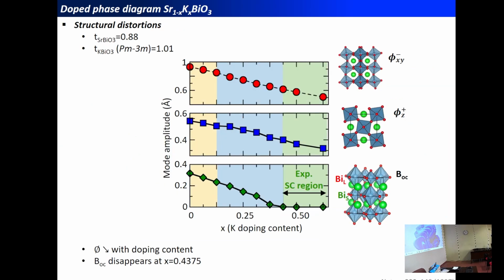So this we can check from the structural analysis we can do on the materials. We can check the amplitude of the lattice distortion associated with the octahedral rotations, but also with the breathing distortion, which is related to the asymmetry of the electronic structure of the two types of bismuth cations. For the octahedral rotation, what we see is that when we put more and more potassium in the material, their amplitude is decreasing. This is expected since the tolerance factor of potassium bismuthate, if it would exist as a perovskite structure, would be close to 1, meaning that this material would prefer to adopt the perfect cubic cell without any octahedral rotations.